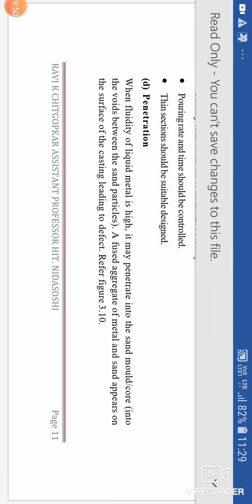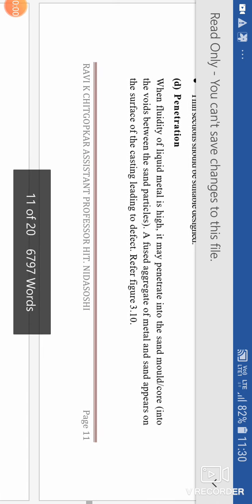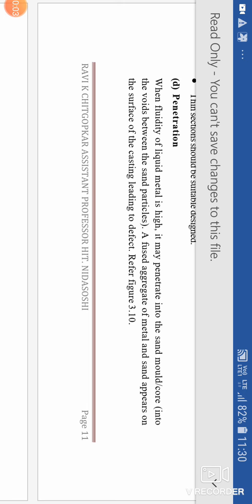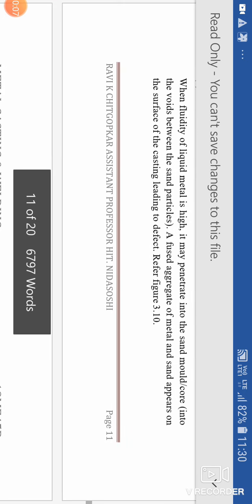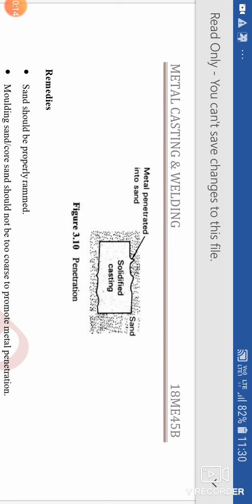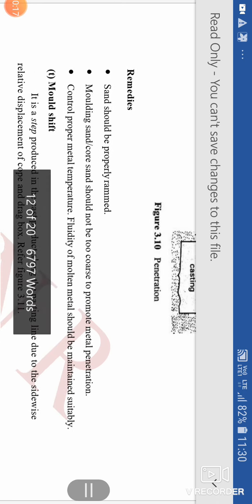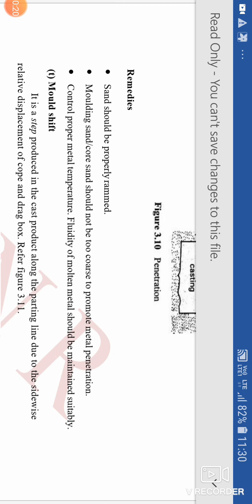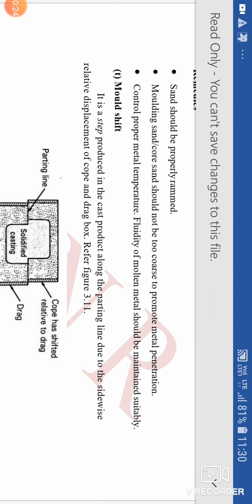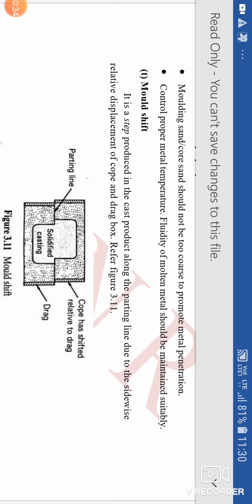When fluidity of the liquid metal is high, it may penetrate into the sand mold or core, into the voids between sand particles. A fused aggregate of metal and sand appears on the surface of the casting, leading to defects. Refer figure 3.10. Solidified casting. Yes, penetration. Remedies. Sand should be properly rammed. Molding sand or core sand should not be too coarse, to avoid promoting metal penetration. Control proper metal temperature. Fluidity of molten metal should be maintained suitably.